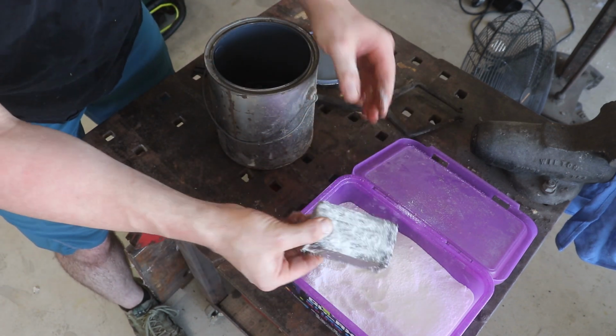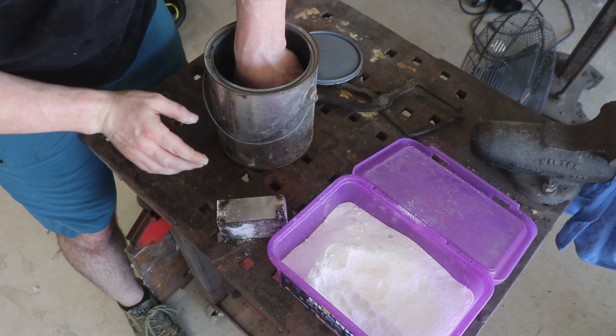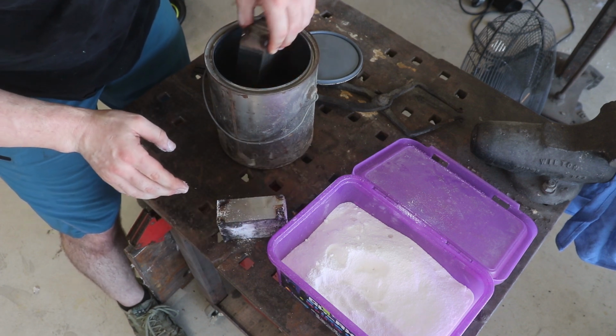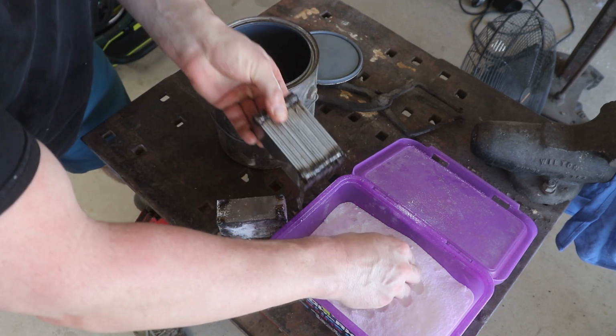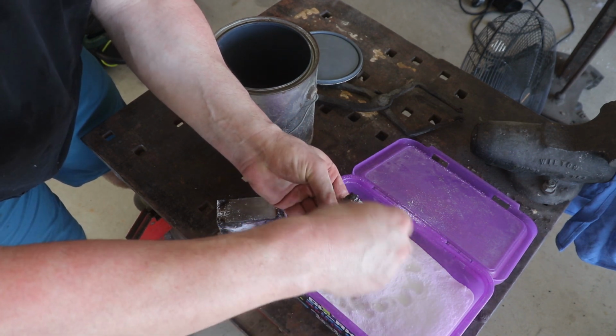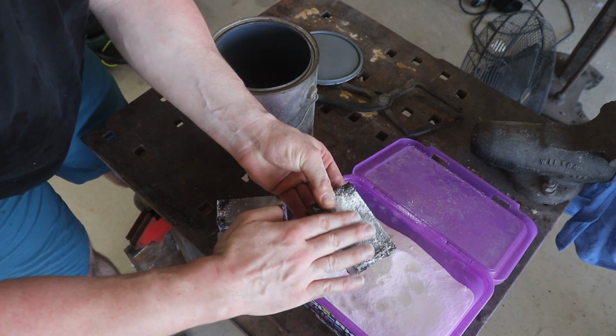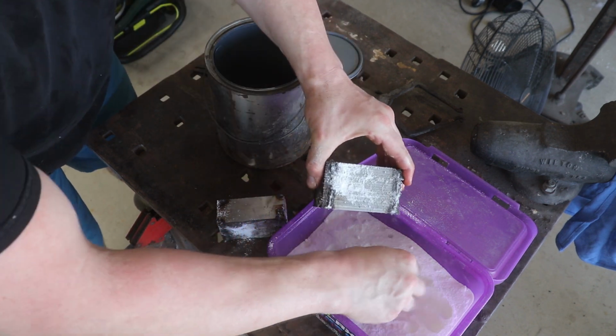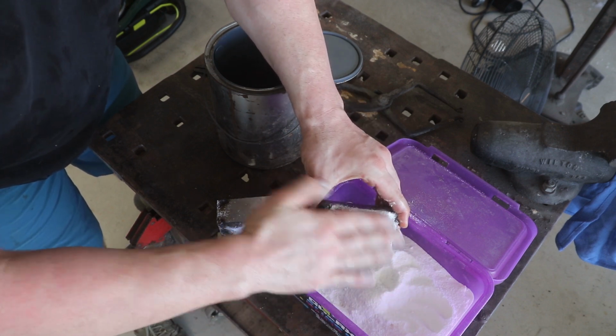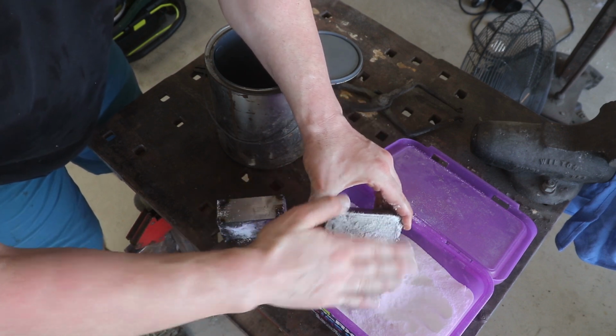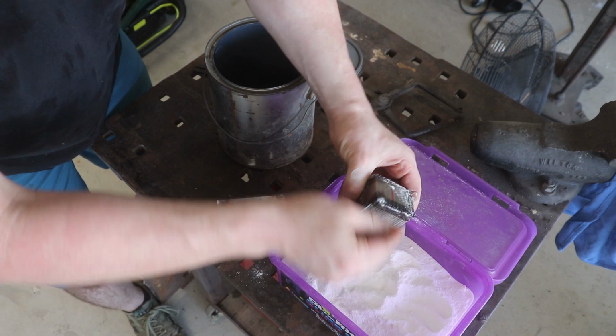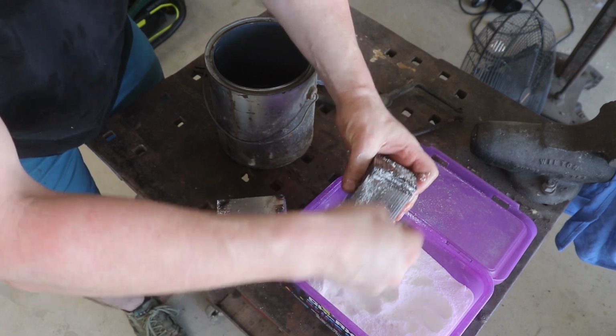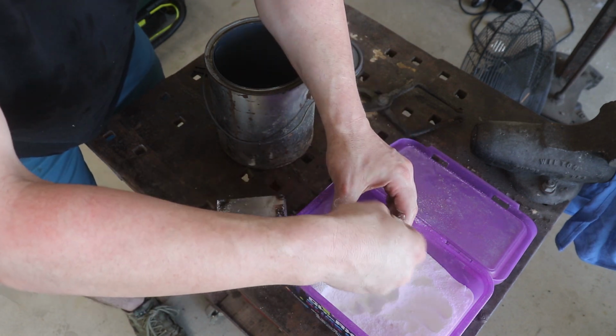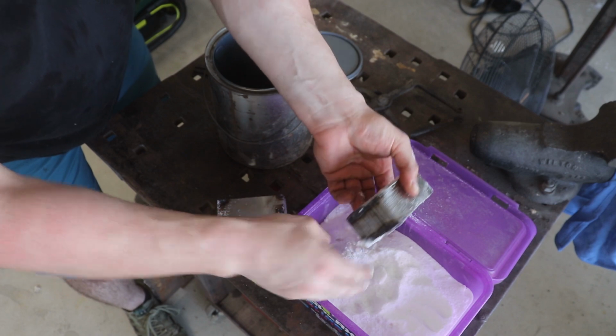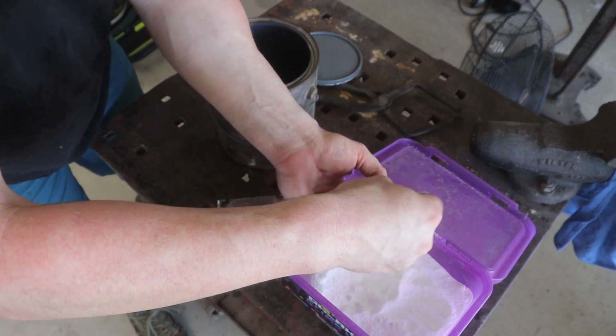And now I'll go ahead and pop this in the forge and I'll heat it up, but not all the way to welding temp. First thing I'm going to do is heat them up until they're just starting to get red hot, and then I'll take them over to the press and smash out any air gaps that are in between these pieces of metal. Make sure that we allow oxygen as little opportunity as possible to get in between there. And that'll stop the oxidation from forming and give us better chances of having a successful weld.